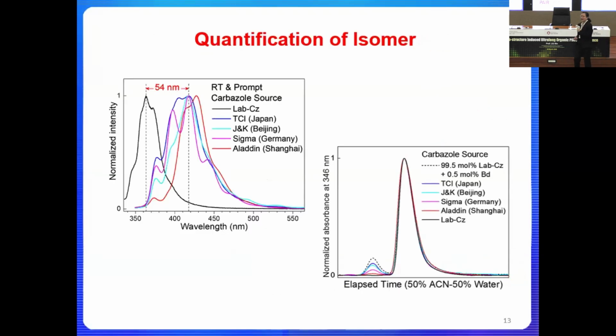Now, if we further quantify the presence of the small fraction of the impurity, you will find out that even in a very, very small amount, its impact is very big. So in terms of the emission, this whole group is the commercially available carbazole that gives you the emission, right? And then this one is the purified one. So the difference is literally 54 nanometers. And we can also quantify the percentage of the impurity. The amount of impurity that exists in carbazole actually varies from 0.1% to 0.5%.